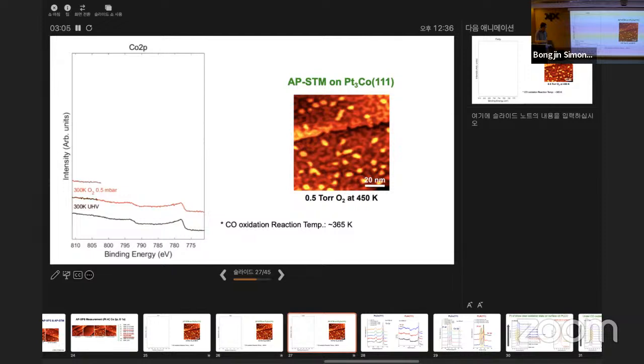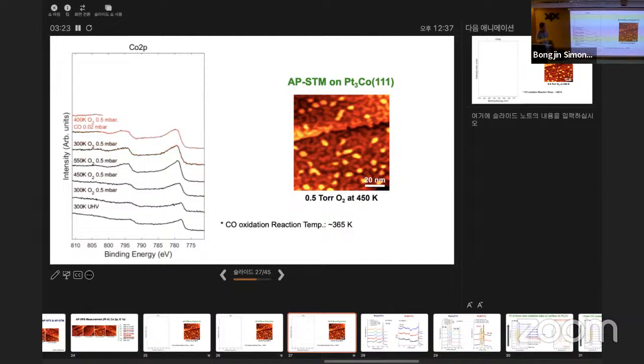And when we introduce this oxygen, 0.5 millibar, same pressure, you can start to see a little broadening. And if you follow the edges of the metallic state, you can see it slightly shifting backward. And clearly, when you introduce 550 K and 0.5 millibar of oxygen at this temperature, this represents the cobalt coming up to the surface and getting oxidized.